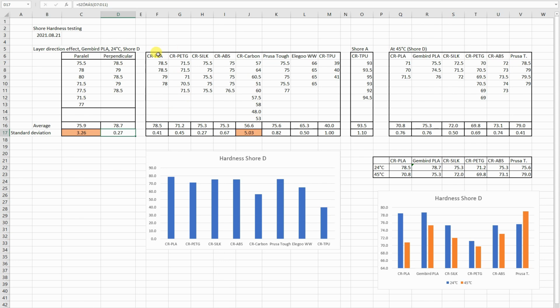In the next experiment I tested these materials, and here you can see the hardness, and it can be seen on this graph too. And here the standard deviation, which is okay in almost every case except the carbon fiber, and I explained that. The reason is that sometimes the indentor hits the carbon fiber, sometimes between, so the hardness is not constant in this case. The last one was the CR TPU, which was Shore D 40 hardness, and then I measured with the Shore A durometer, and here I got 93.5 hardness.